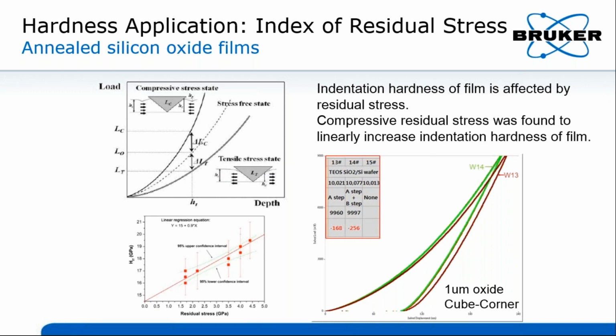Here, we have 2 wafers of 1 micron silicon oxide films undergoing different treatments. The type 1 stress was measured using the warpage method, and the value of stress is shown here. Wafer 14 has higher compressive residual stress compared to wafer 13.